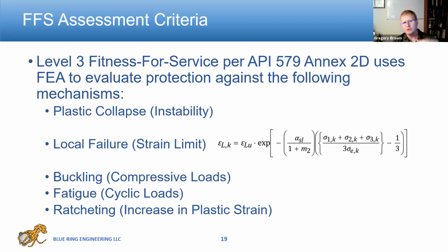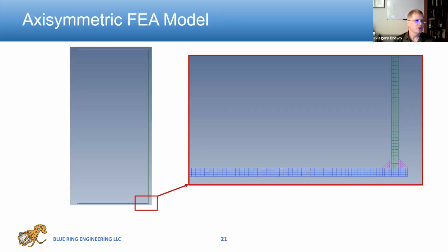If you have compressive loads pushing on the structure, you have to make sure the structure wouldn't buckle and fail that way. If you have cyclic loads, so the pressure is oscillating, for example, you would need to do a fatigue evaluation. Oscillating loads can also cause what's called ratcheting, where on each cycle you start getting more and more strain, and this actually causes a low cycle fatigue failure, where the structure could actually fail in a relatively low number of cycles. So here's an example of a computer model.